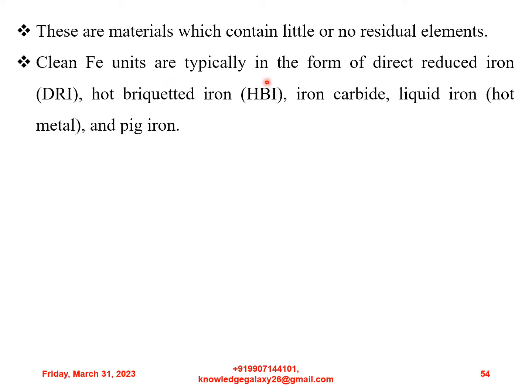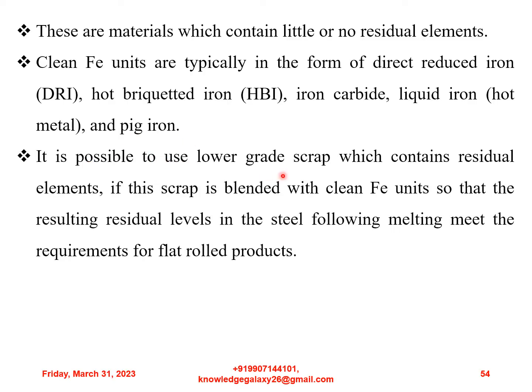Clean iron units are typically in the form of direct reduced iron, that is DRI, hot briquetted iron HBI, iron carbide, liquid iron, hot metal, and pig iron. It is possible to use lower grade scrap which contains residual elements if this scrap is blended with clean iron units so that the resulting residual levels in the steel following melting meet the requirements for flat rolled products. Obsolete scrap is much more readily available than prompt scrap and hence the demand for clean iron units is always there.